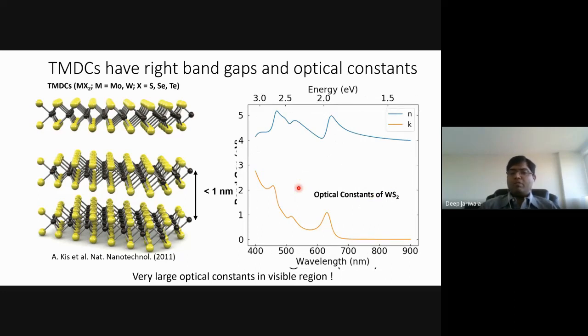But more importantly, when you start looking at their optical constants more closely, you find out that even in the bulk form, so if I take a bulk crystal of these materials, due to the van der Waals bonding, the wave functions are so well isolated that the optical spectra are still dominated by excitons over here.